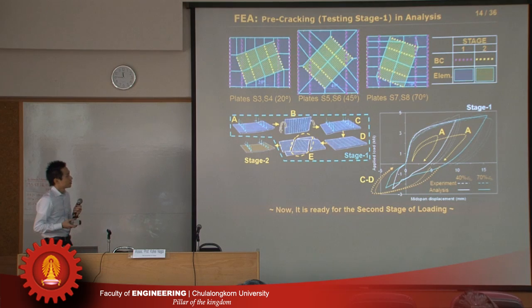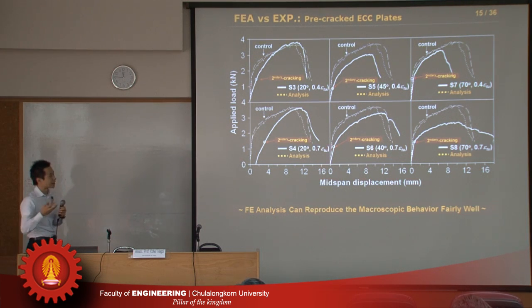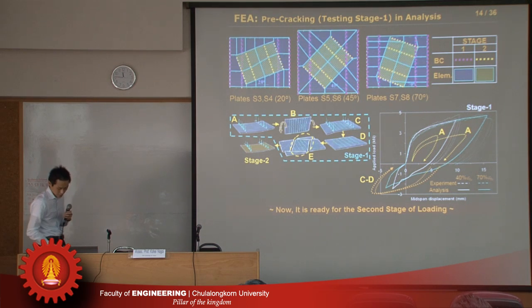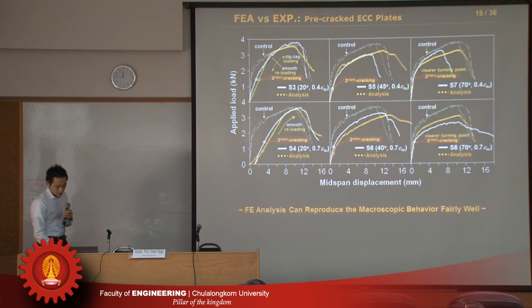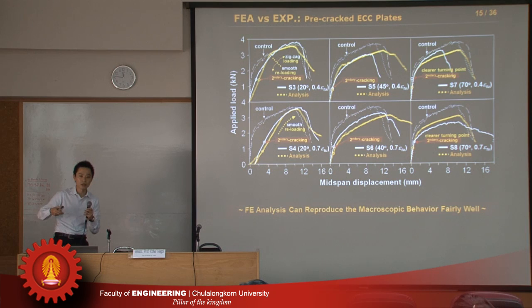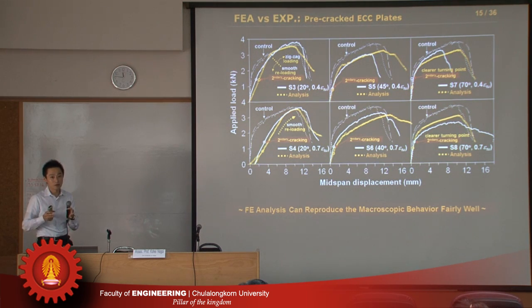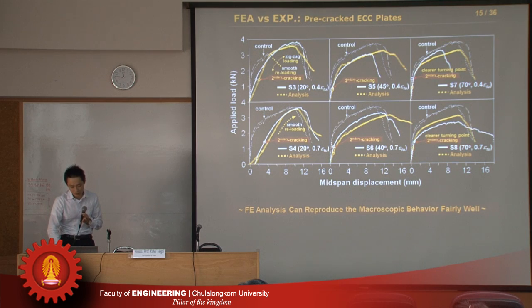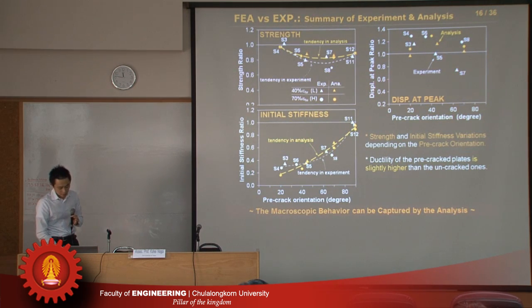So firstly, we did the analysis of the plate test. The result is just a result, so I quickly show you. We could simulate exactly the same loading history of the experiment like this. This is a rotated case, but anyway, the white line is the experiment and the yellow line is the analysis. So we could simulate the secondary loading as well. Actually, before that, we did the first loading by simulation. Then after that, we change the loading condition in the simulation, and we can simulate this phenomenon. The reduction of stiffness and strength, the tendency is well represented. Yes, this is, again, a comparison.